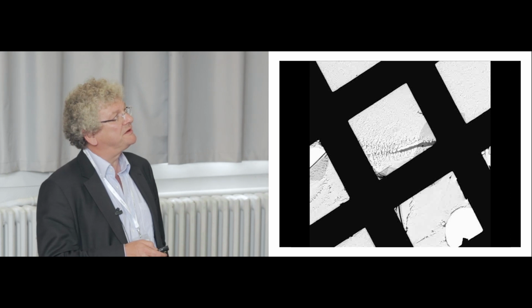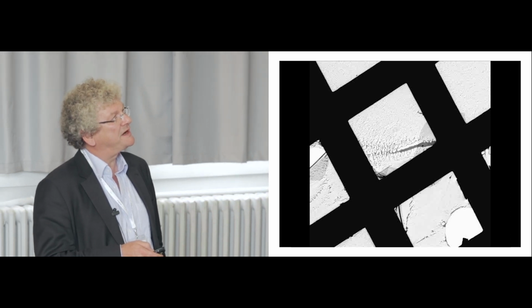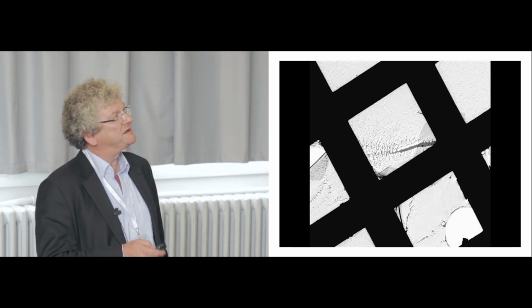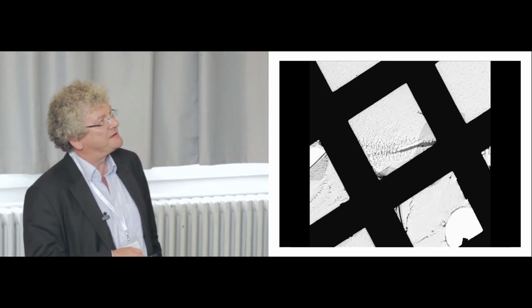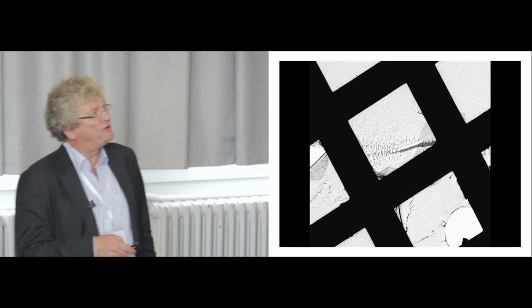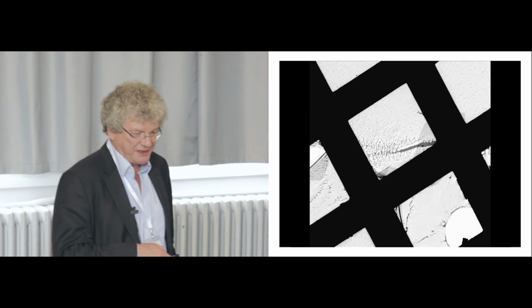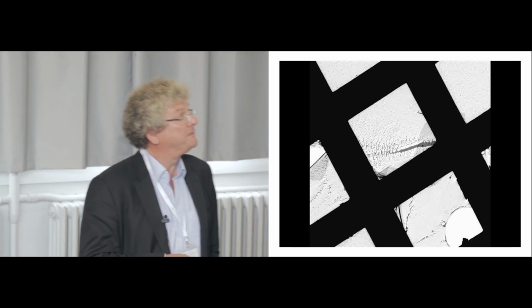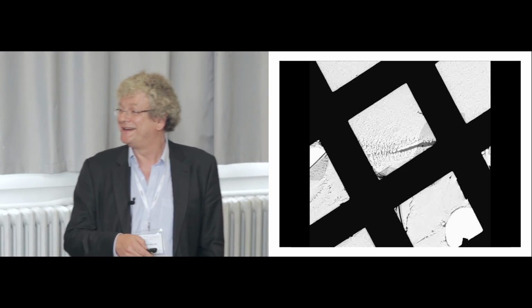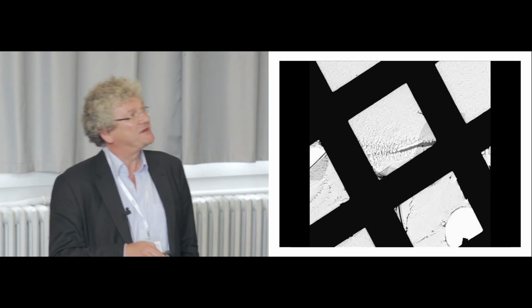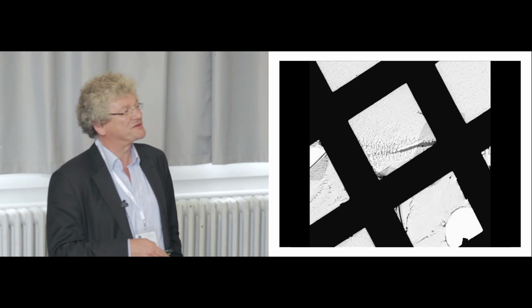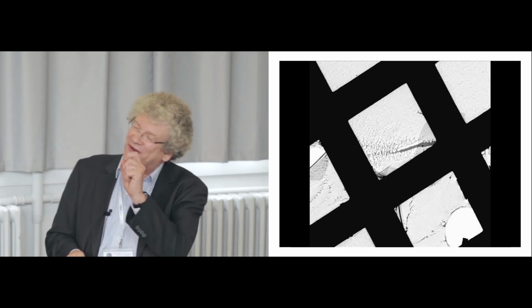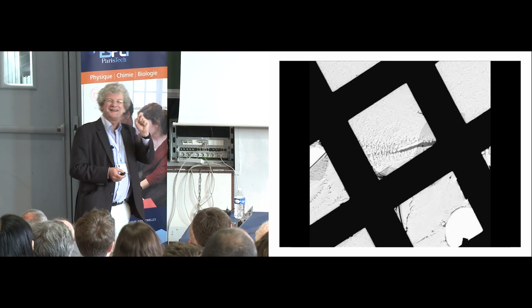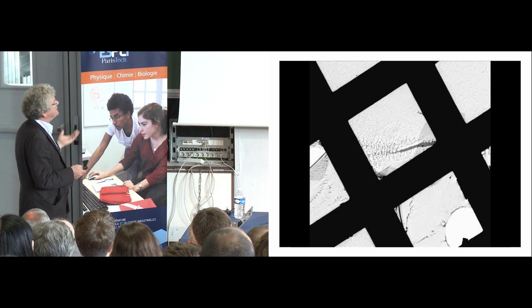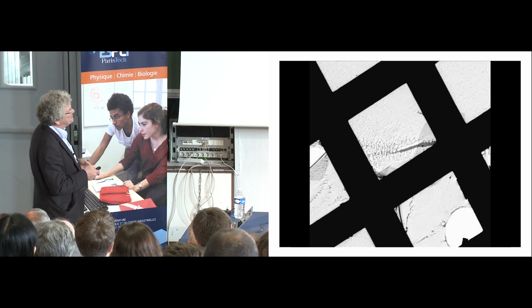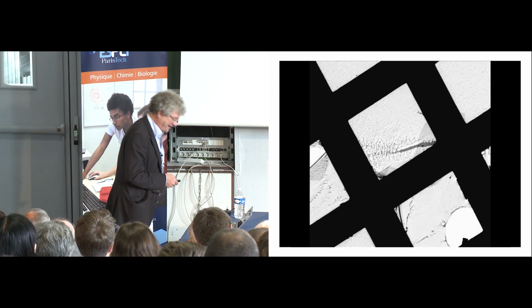Monodisperse, single crystals. Now the crystal lattice planes will show up, faceted surfaces, and almost perfect crystalline structures. So here the iron atoms are seen. So this is what you can do with these modern electron microscopes. And at that time, we just saw, oh, there were these tiny dots, and these were the particles. So actually, something like this we were happy to see as a particle and not as an atom.